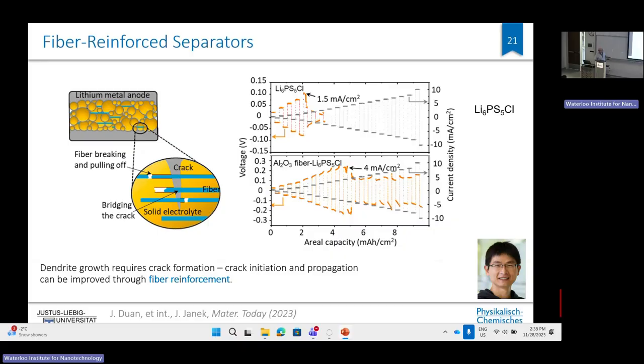And in fact, in these kind of dendrite tests, he could extend the lifetime of the separator to higher critical current densities, because these fibers simply, even if a crack initiated, the crack didn't grow as fast as it would grow in a simple separator. And as I see Mike Pope here, he has just this week had a workshop running on 2D materials. When I put the slides together, I thought maybe 2D materials could be something that helps strengthen the separators and improve the chemomechanics of a separator. So that's maybe something worth being discussed.